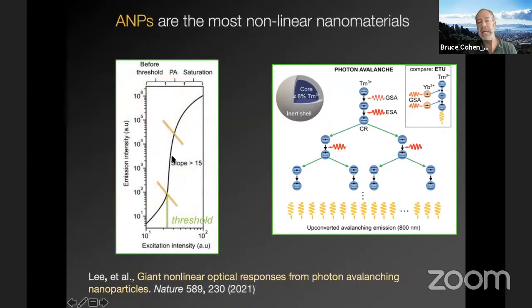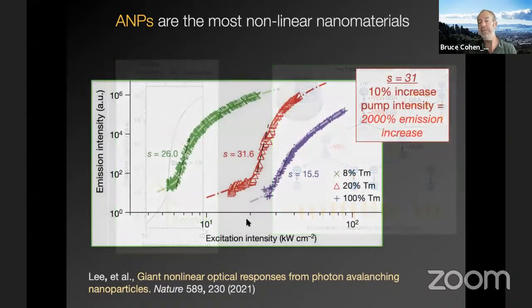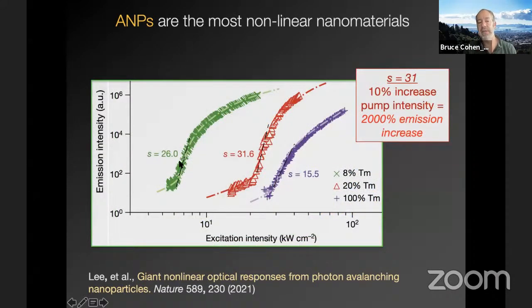And it becomes photon avalanching if the steepness of that nonlinearity, so this is a very nonlinear process, and in fact, it's 15. In other words, the emission intensity is the 15th power of the excitation intensity as you change it along that threshold. So that's the definition of an avalanche. We made nanoparticles, we did these experiments, and we were actually able to find cases where the emission intensity was up to about the 32nd power of the excitation intensity, while you are in the avalanching part of the S curve.